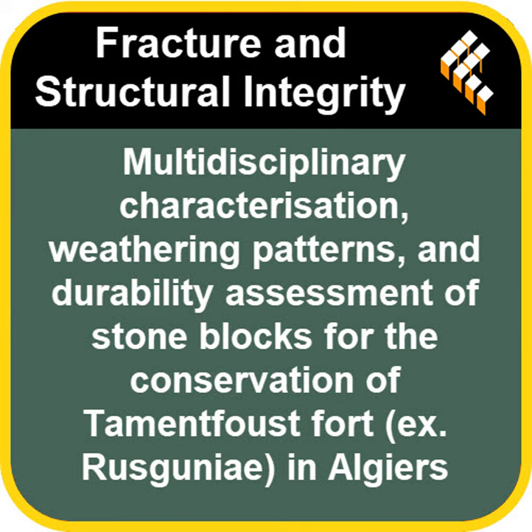So chemically, what's actually happening? How does acid or salt weaken it so much? Well, chemically, the hydrochloric acid reacts really vigorously with calcite, which is the main component of both stones. It basically dissolves the stone's natural glue. It produces CO2 gas, water, and calcium chloride, which is soluble and just washes away. Salt does something similar. It reacts to form other soluble compounds that leach out, leaving the stone fragile. So it's like the skeleton of the stone is being dismantled. That's a good way to put it. Even the tougher minerals, like quartz, can slowly alter over time into weaker clay minerals. It's a constant chemical assault.